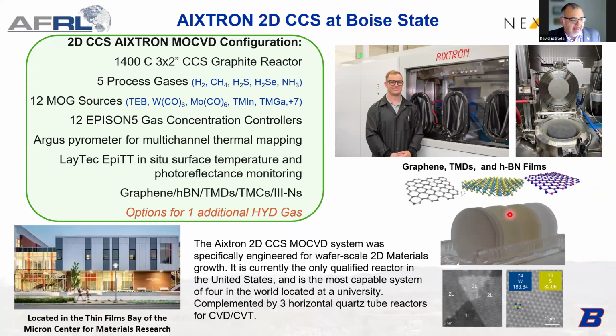So our tool here at Boise State was qualified this February. We purchased the Aixtron 2D close coupled showerhead. You can see how it's configured here, but we have 5 process gases: hydrogen, methane for graphene growth, transition metal carbide growth, hydrogen sulfide, hydrogen selenide, and ammonia for gallium nitride growth, right? We have 12 metal organic sources. Right now we have triethyl boron, tungsten and molycarbonyl, trimethyl indium, and trimethyl gallium on the tool with room for expansion.